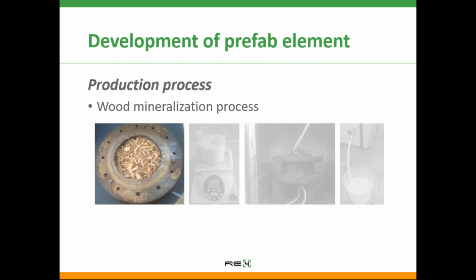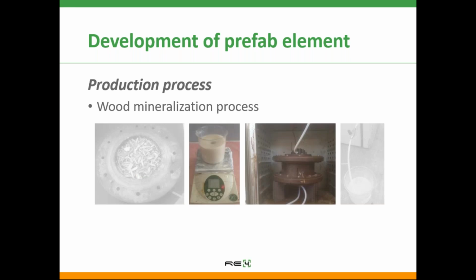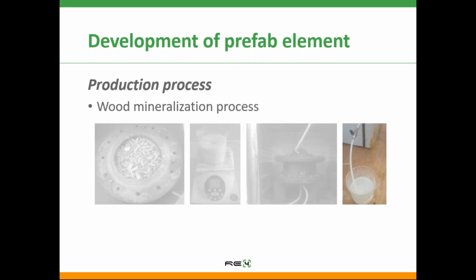The mineralization process was carried out before soaking the wood in water for the insulation panel production process. In detail, wood was kept in an autoclave under vacuum to obtain the degradation of wood fibers. Then the injection of mineral suspension in the autoclave was realized. The autoclave was pressurized in order to force the mineral solution to soak the wood fibers. And then the mineral suspension was removed and the autoclave depressurized.